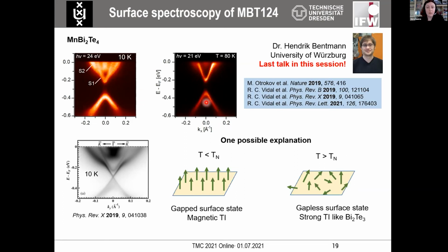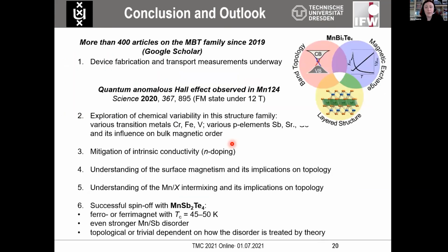So there are some intricate things with a gap being opened in the paramagnetic state, or some other samples different from ours being reported to have a closed gap in the ordered state. There were possible explanations for that in the literature, pertaining that there could be some disorder of the moments at the surface of the samples. I think that nowadays we can also safely say we should look more into disorder, into intermixing in the samples to maybe be able to explain these discrepancies in spectroscopy.